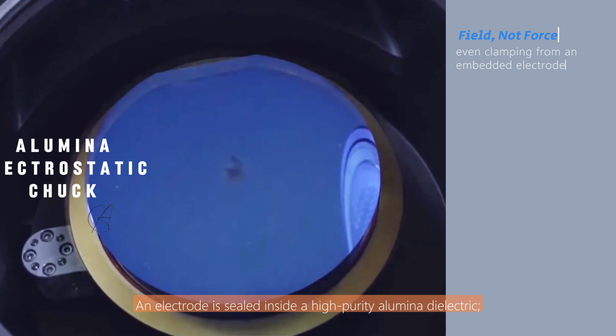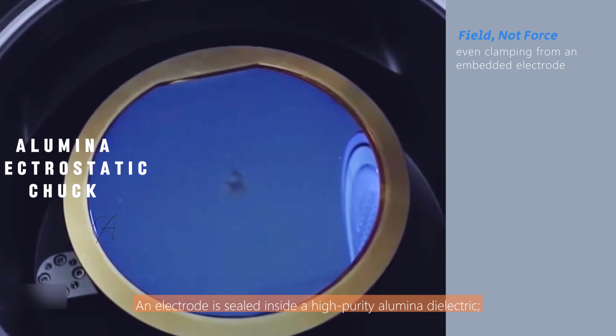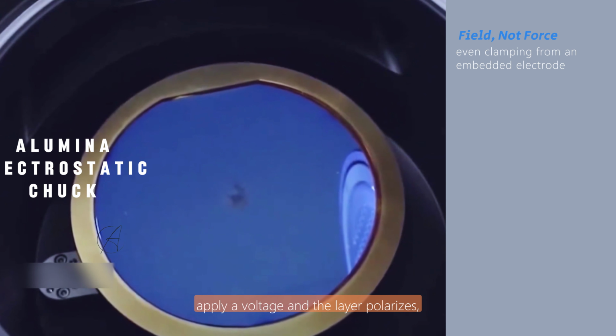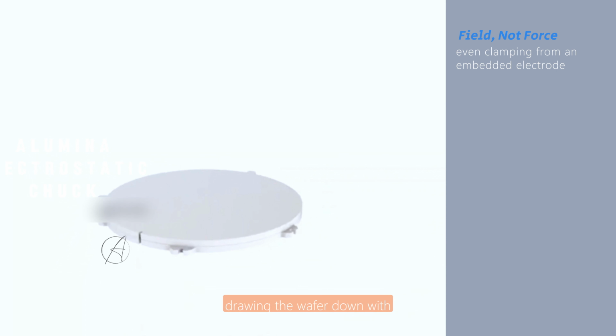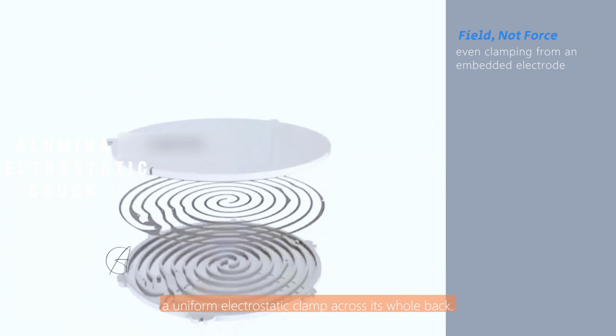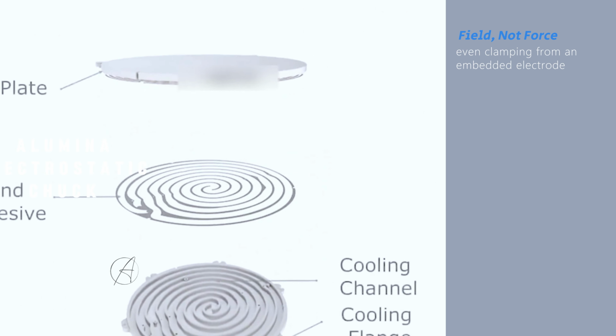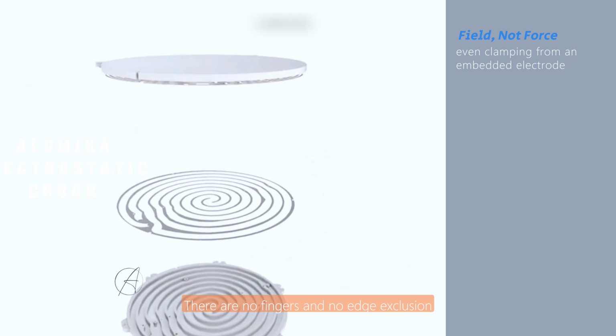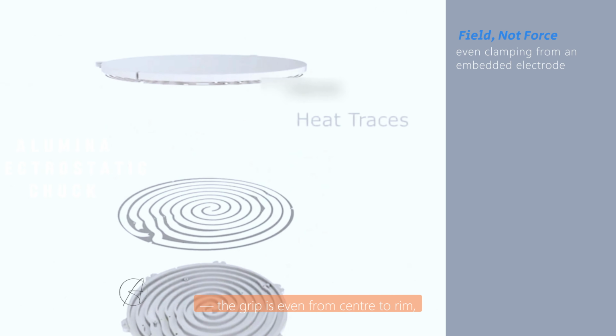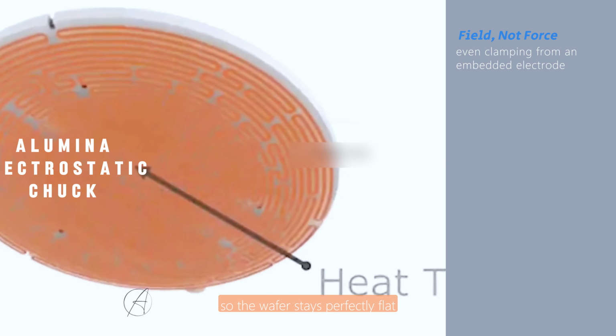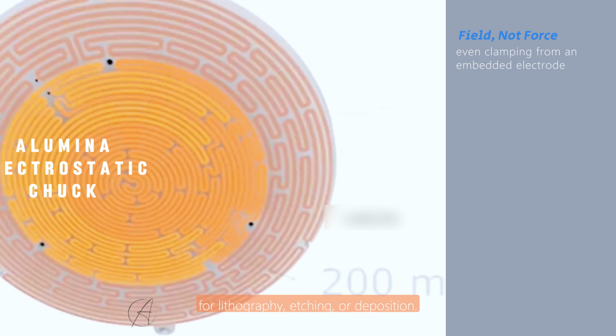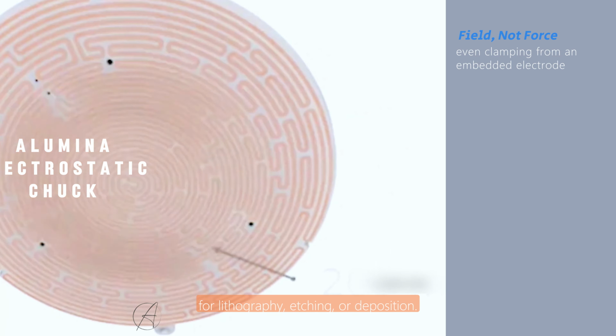The hold comes from physics, not pressure. An electrode is sealed inside a high-purity alumina dielectric. Apply a voltage and the layer polarizes, drawing the wafer down with a uniform electrostatic clamp across its whole back. There are no fingers and no edge exclusion. The grip is even from center to rim, so the wafer stays perfectly flat for lithography, etching, or deposition.